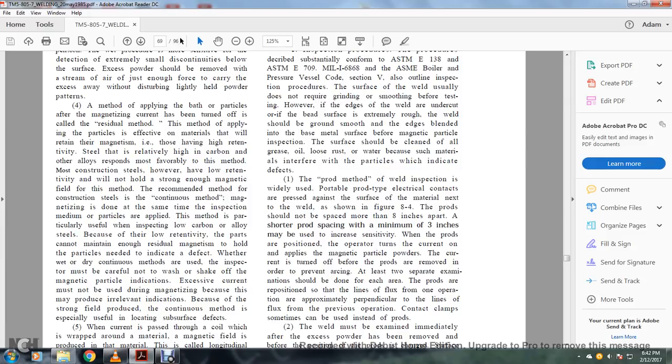4. A method of applying the bath and particles after the magnetizing current has been turned off is called the residual method. The method is effective with materials that retain magnetism, those having high retentivity. Steel that is relatively high in carbon and other alloys responding more favorably to this method. Most construction steels, however, have low retentivity and will not hold a strong enough magnetic field with this method. The recommended method for construction steel is the continuous method, where magnetizing is done at the same time as the inspection and particles are applied. The method is particularly used for inspecting low carbon alloy steels because of the low retentivity of the parts, which cannot maintain enough residual magnetism to hold the particles needed to indicate the defect.